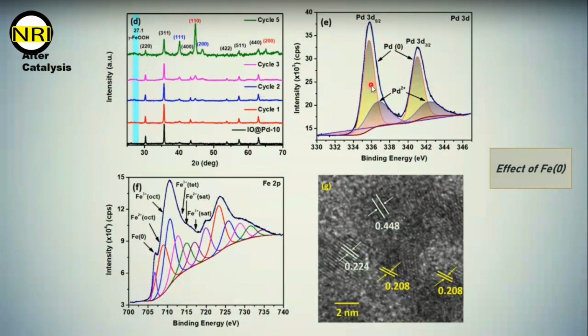This is the palladium XPS of the used catalyst, and we can see that palladium 0 nanoparticles are there along with some palladium 2+. This is due to palladium hydroxide formation over the palladium surface, because we have done this reaction in water. So some hydroxide, some water is still deposited over the palladium. This is why this palladium 2+ is coming.